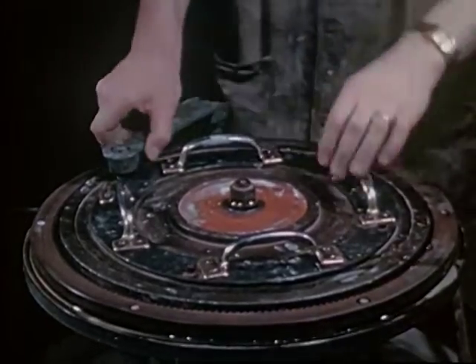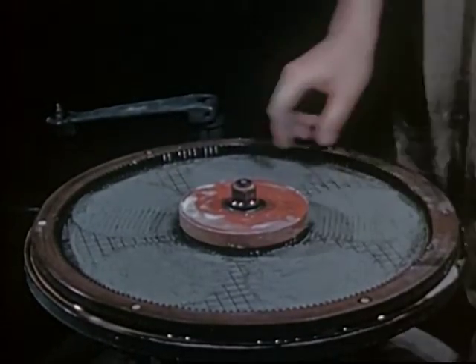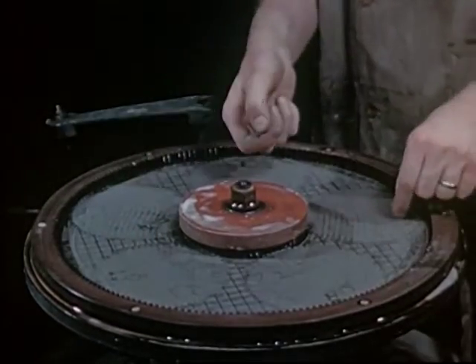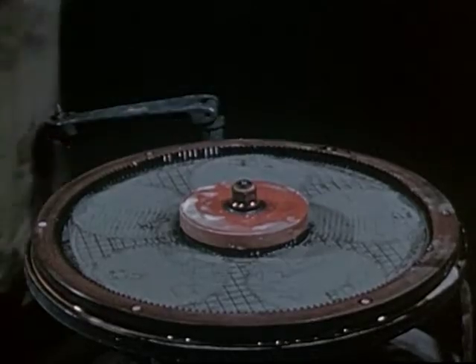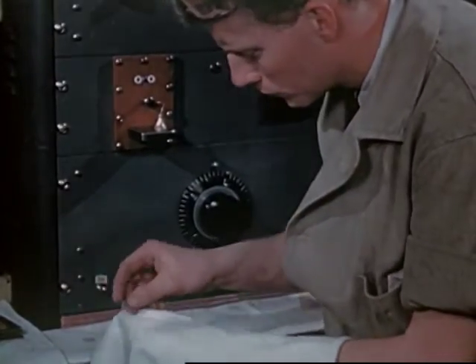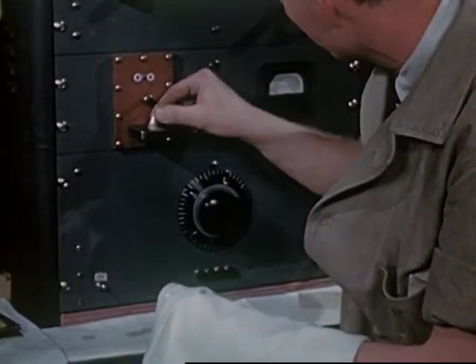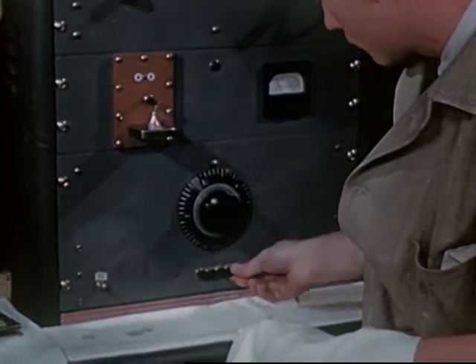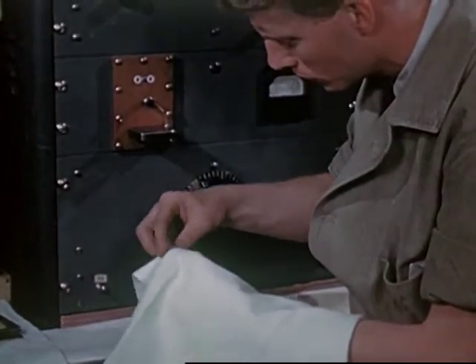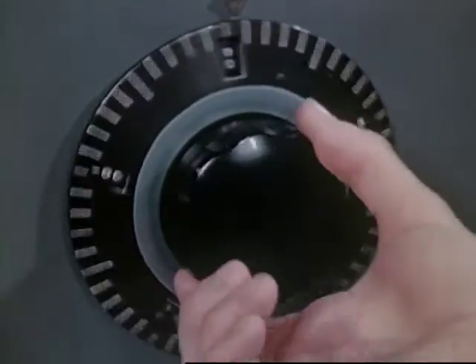When the time of lapping has ended, the operator deftly lifts off the top lapping plate and removes one sample blank from each of the 5 holders. These are cleaned and tested between metal electrodes in an oscillating circuit. Upon adjustment of the dial, the meter tells the activity of the blank, and at the same time, an audible tone indicates the frequency by comparison with the standard.